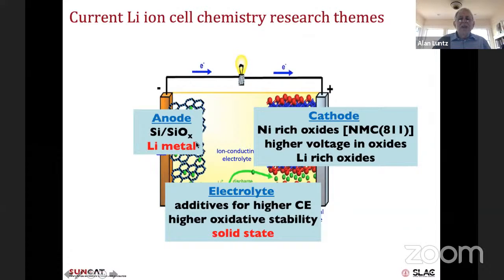However, whenever you change the anode, you have to go through that all again. So there's a lot of work now going on to try to optimize the electrolytes for silicon anodes, for lithium metal anodes, and so forth. And of course, trying to get a higher oxidative stability so you can use higher voltages in the cathodes.